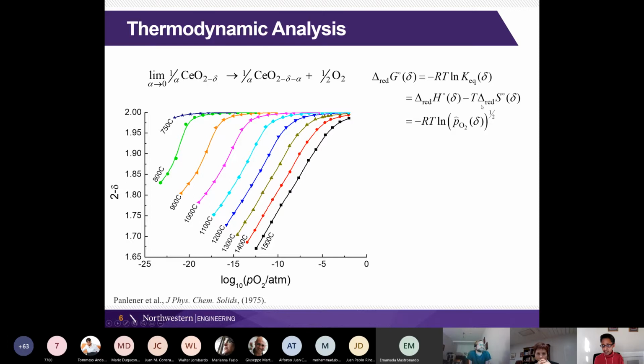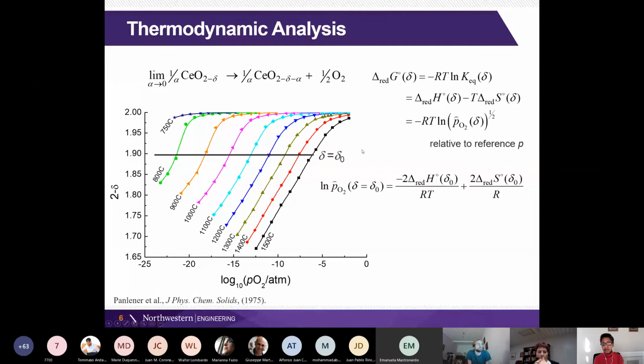So here's our delta H and delta S. So we can write that out as just being RT ln PO2 to the 1/2, because that's what we get from here. And these two sides are equal, so they don't enter into the equilibrium constant here. Okay, so we're going to evaluate this at a given delta, and this hat here means that this is relative to the reference pressure, which is 1 atmosphere. Okay, so let's evaluate it at a given value of delta naught.